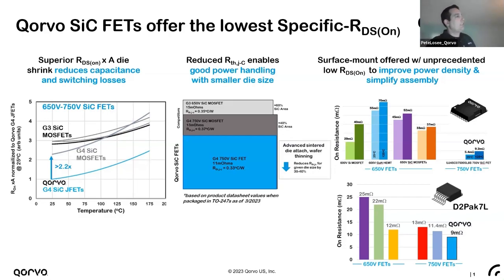And so if you look at the plot on the right or the left, you'll see the silicon carbide JFET as the baseline or the unit of one, and then the other 650 or 750 volt offerings normalized to that value. And so a significant RDSA advantage at room temperature. More than 2x higher for the latest silicon carbide MOSFETs at 750 volts. And the other thing you'll notice is that the temperature dependence of that RDS-on is a bit steeper than its peers. And there's a reason for that.